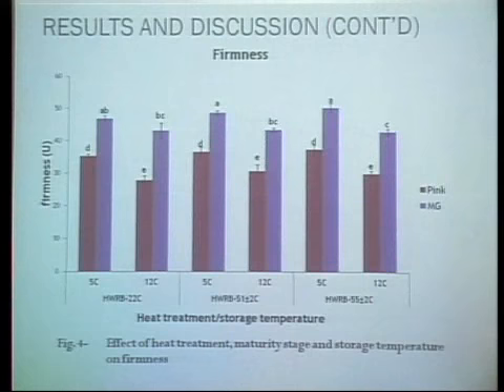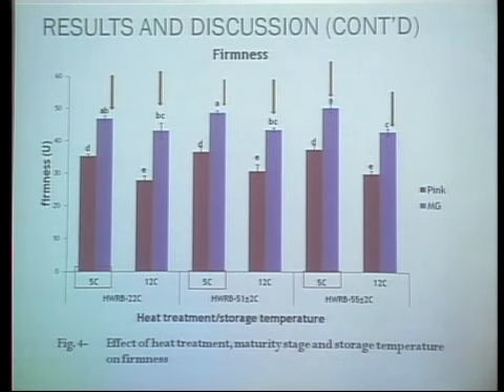And then for the firmness, we didn't have any interaction between the heat treatment, the storage temperature, and the maturity stage. Sorry, between the heat treatment and the storage temperature, but there was a significant effect of the maturity stage. And as you can see, at 5, the storage temperature had a significant effect. At 5, you can see that the fruit were much firmer, both in pink and in the matured green. And then the matured green was much firmer than the pink fruit, that is after storage in all the temperatures.